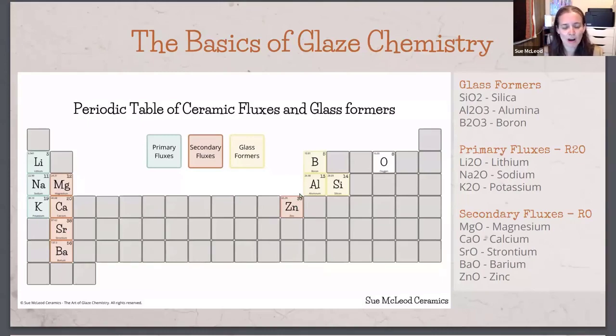So these all fall in the same column. Zinc is over to the right. There's always anomalies and special cases in ceramics. So the primary fluxes are the really active melters. They are what get the melting started as the kiln temperature goes up. The secondary fluxes are also melters, but they kind of keep the melting under control, and they're not as powerful as the primary fluxes. If we were to use all primary flux and no secondary flux, the glaze would just start melting, and before we knew it, it would be running all over the kiln shelf. So we add secondary fluxes to kind of control the melting so it doesn't happen so fast.